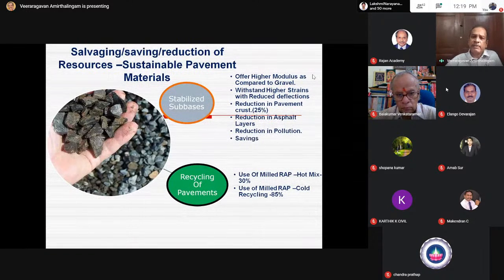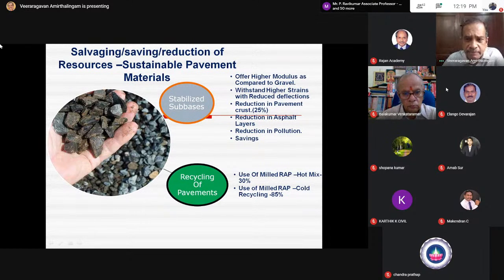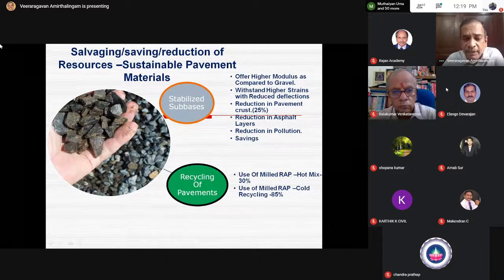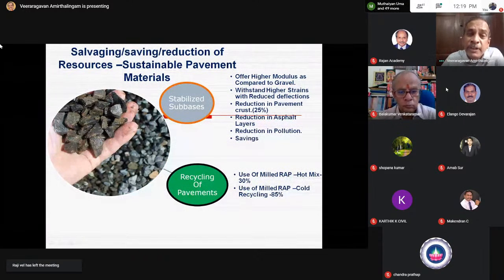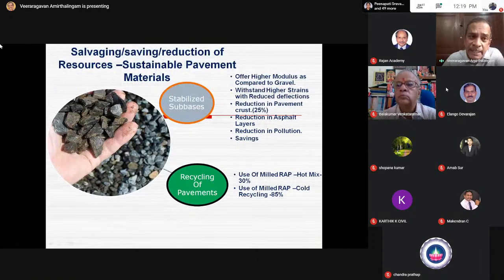So there are possibilities of having a higher modulus in this case when compared to the conventional granular base. I was mentioning you can go in for a stabilized subbase, and you can also have modified binders which can withstand higher strains. Is it possible to reduce the strain values? Yes, these will reduce the pavement design thicknesses significantly. Will there be a reduction in the asphalt layer thickness? Yes. Will it result in reduced pollution? Yes. Will it result in saving in cost? Yes. So we should move towards sustainable pavement materials and sustainable design by having alternate designs.